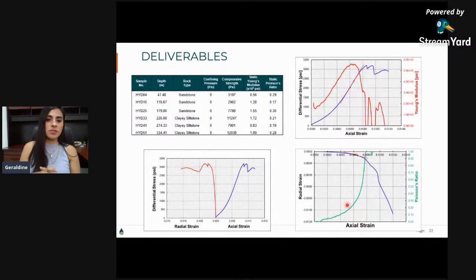How do the deliverables look? Okay, the deliverables look like this. You receive a chart with your sample depth. Sometimes we give the rock type and the confining pressure. In this example, it is for UCS, which means unconfined compressive strength test, no confining pressure applied. Then you have the total peak of compressive strength, the Young's modulus, and the Poisson ratio. This graphic is the representation of the test.